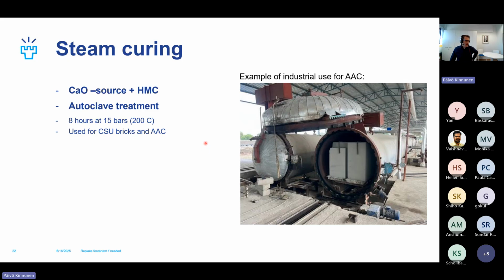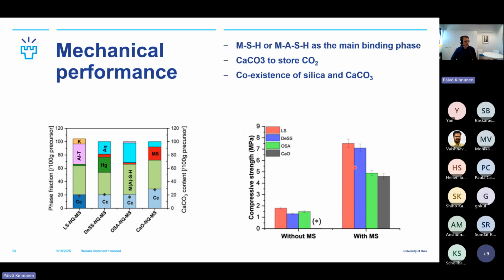And in terms of curing, we went for steam curing, which is just an autoclave that's shown here, used for autoclaved aerated concrete. It uses about the same pressure and temperature, so it's 15 bars at 200 Celsius, for 8 hours. And this is also used for calcium silicate bricks. Surprisingly, this is a quite low energy route, because you can recycle the steam, and also the reactions that happen are exothermic. Those are happening at high temperature, so you can recover the heat. So this is a surprisingly good process.